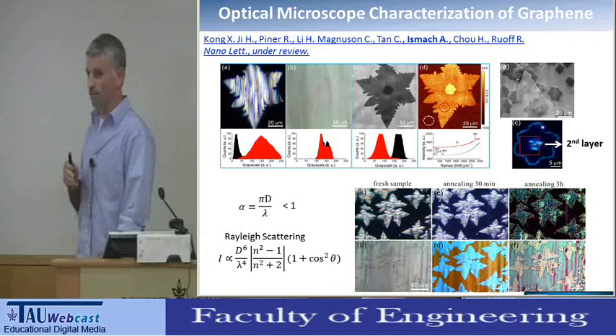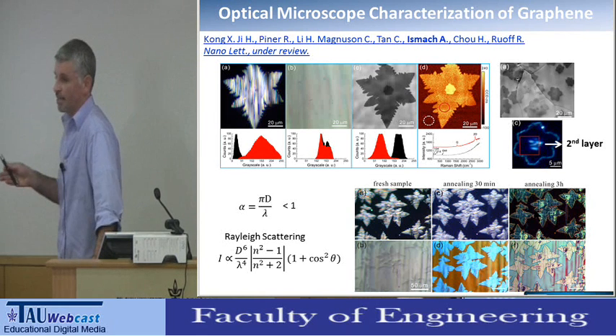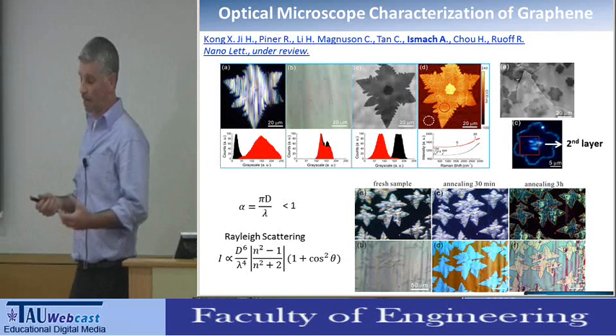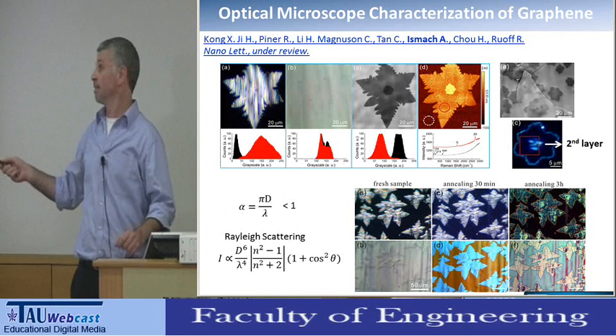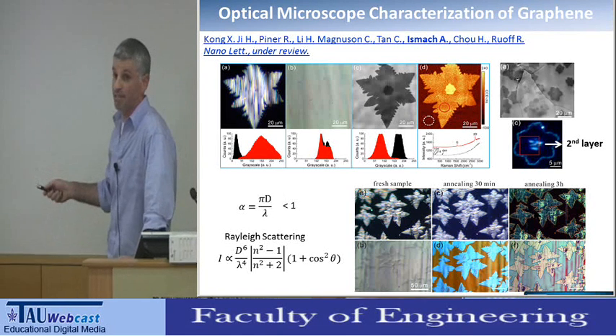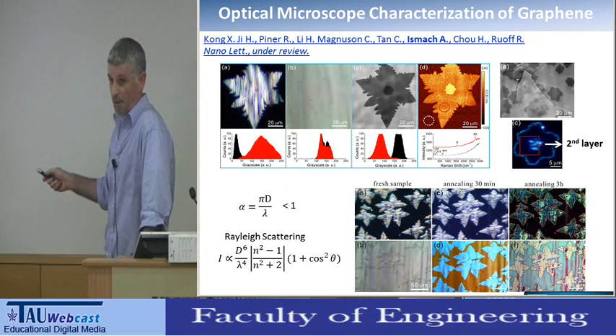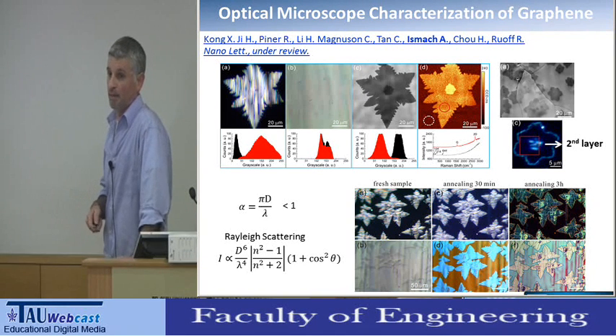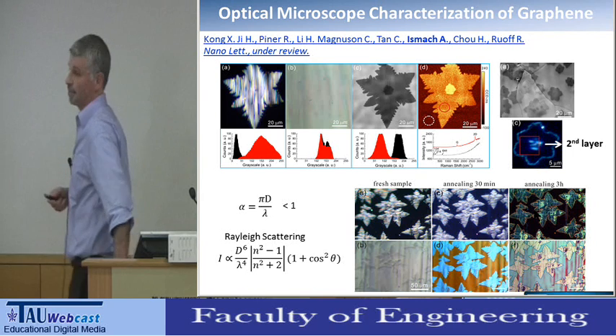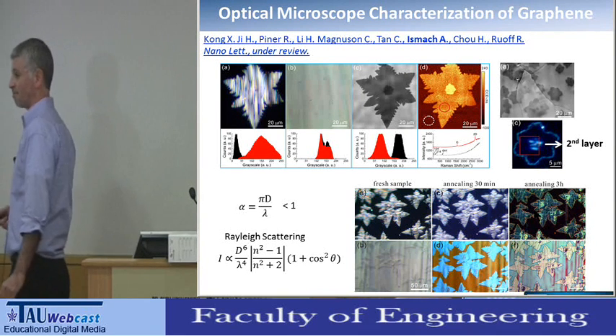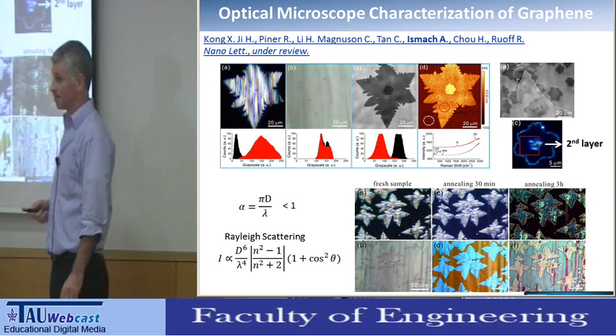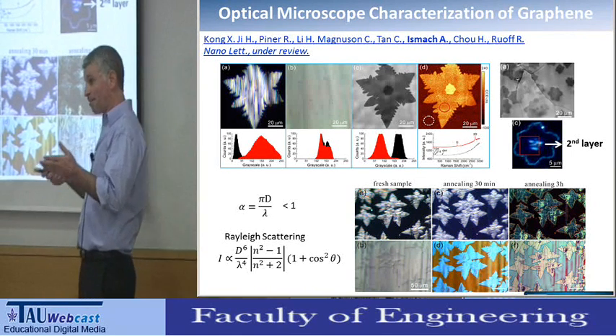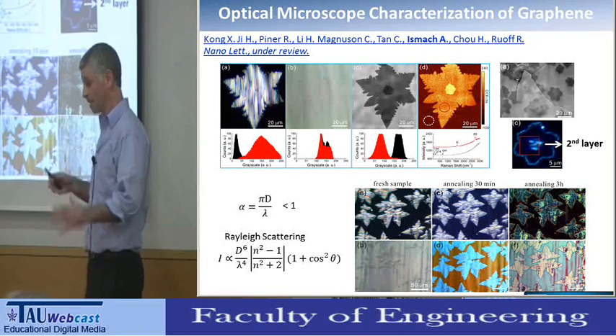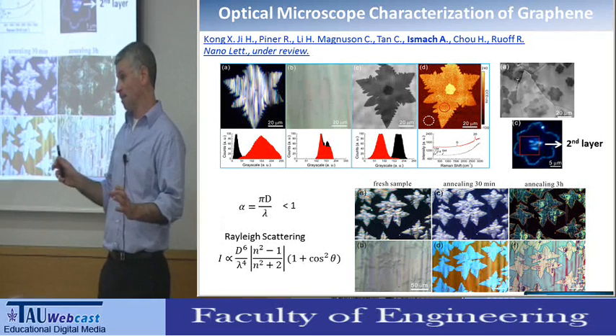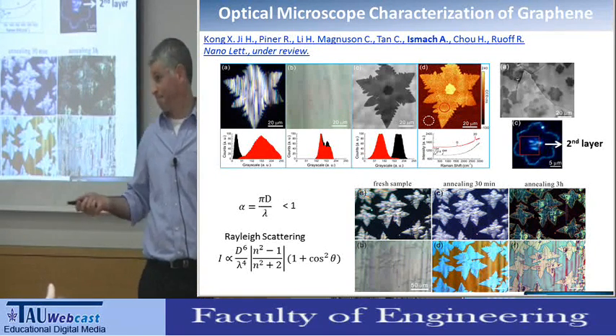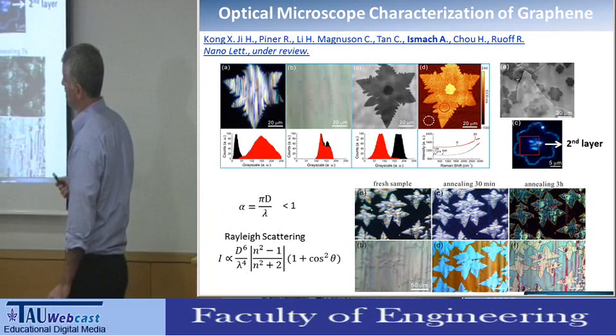And I can talk about the reasons for hours. One of the reasons is the impurities of the copper actually etch away some of the graphene, and that's why in this copper, which is less pure, you can achieve much larger domains than in high purity copper. We can talk about that later. I didn't mean to talk about that in this. More like dendrite growth along the symmetry direction of the crystal. Yeah, but when you use a high purity copper, you don't get a dendritic growth. You get a hexagonal growth. Small domains, but hexagonal. Which means we are back to kinetics. Kinetics determines the shapes of the domains, of course.